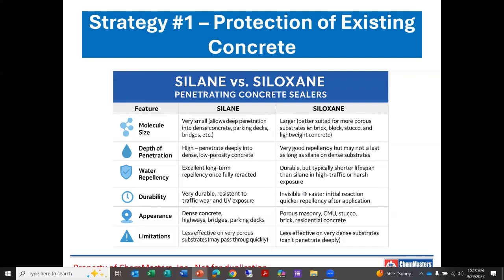The depth of penetration, silane again is going to penetrate more deeply in these dense, low porosity concretes, whereas siloxanes, although they do a fine job, they're not going to penetrate quite as successfully on those dense surfaces. But they do a fine job there, and they can be used more readily in high porosity applications. Water repellency. Silanes have great long-term water repellency once they're reacted.